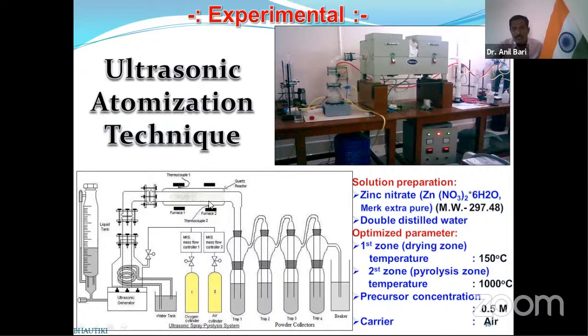This second zone temperature is near about 1000 degrees centigrade, which converts this fine mist into the oxide nanoparticles. That is the zinc oxide nanoparticles, and these particles were collected into a number of traps. These traps are novel because they can sort the nano powder particles size-wise. So the bigger size is here, then smaller, then smaller, then smaller. We can use this smallest size for our preparation of the thick films.